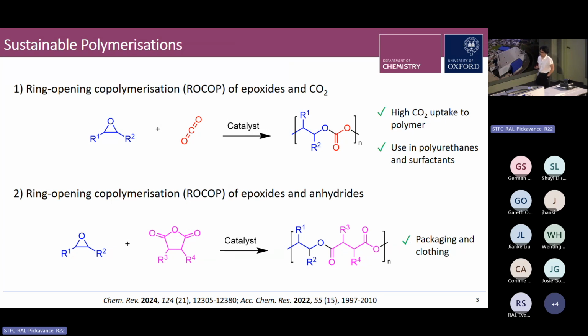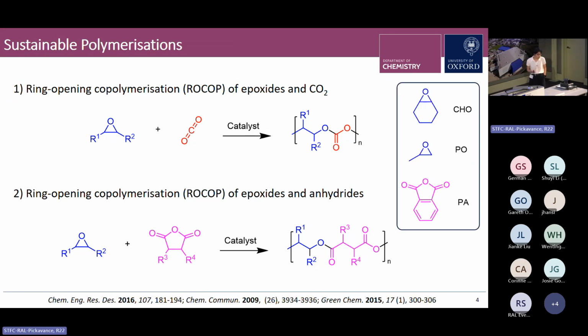But one of the most significant advantages of using processes like these to make polymers is the diversity of chemical structures and therefore polymer properties that are achievable through varying the substituent R using different commercially available epoxides and anhydrides. And the particular epoxides and anhydrides I'll be focusing on in this presentation are, for the epoxides, cyclohexene oxide or CHO, and propene oxide or PO, and for the anhydride, phthalic anhydride or PA. And all three of these monomers are commonly used benchmark monomers in this field of polymerisation catalysis. Bio-based routes to all three are known and reported in the literature, and they're all three commercially available.